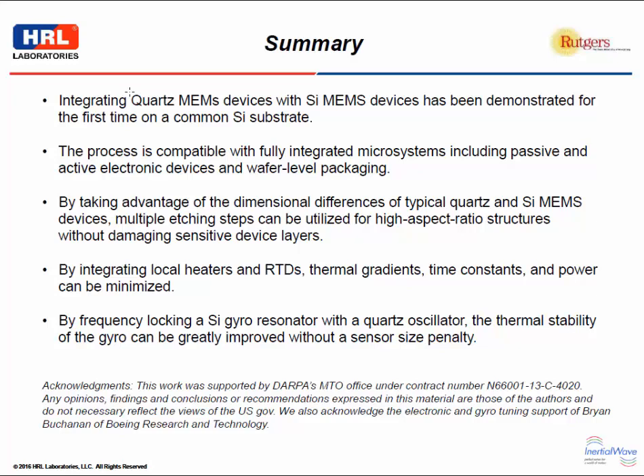By taking advantage of the dimensional differences of the typical quartz and the silicon MEMS devices, these multiple etch steps could be realized for these high aspect ratio structures without damaging the sensitive device regions. As you might suspect, if we had the quartz device outboard of the silicon device, or we didn't have it covered with a protective coating, then that long deep RIE etch of the silicon gyro would really degrade the quartz performance. And we showed we could integrate the heaters and RTDs locally to minimize the time constants and the power. And finally, we're hoping to demonstrate this frequency locking technique soon on another program that we just got started with